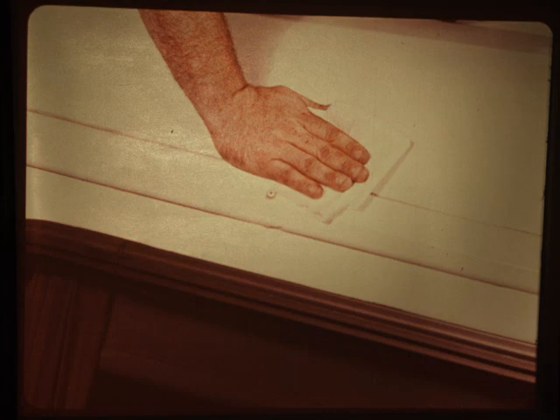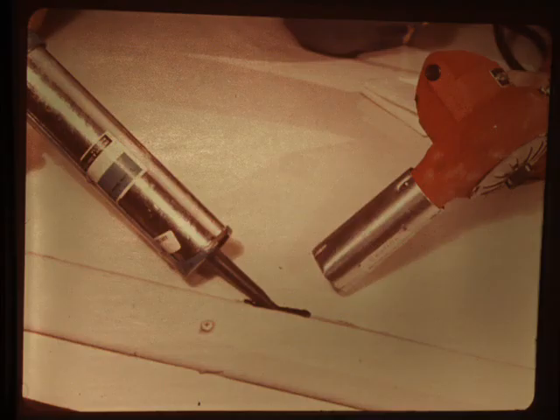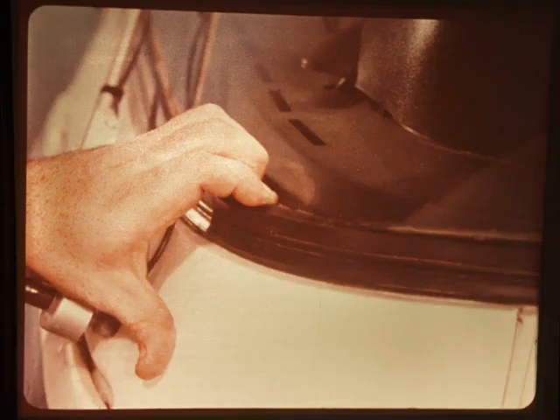The keys to making sure the sealant adheres are 1, to make sure all surfaces are clean, and 2, to be sure the motorhome's skin temperature is at the very minimum 65 degrees. If the temperature is too low, the sealant will not adhere. If necessary, use a heat gun or lamp to maintain the correct temperature.